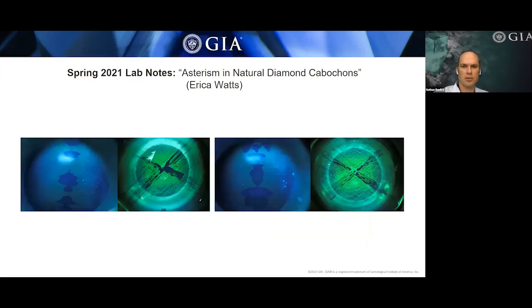And it was also determined that this pair of stones was cut from the same rough, probably from Zimbabwe. And so the DiamondView image showed similar features on both the top of the stone and the base. And so you can see that this was most likely sliced from a single crystal, where the crystal was cut in half and each of the halves was polished into this cabochon.